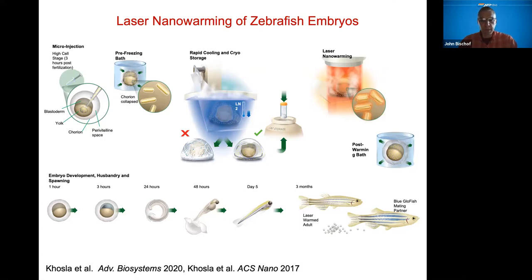So for the zebrafish, this is particularly exciting because, as I mentioned, no one has actually been able to cryopreserve this system, and many people have tried. So we finally were able to do it in 2017. We brought back embryos that were actually intact and growing, although none of them hatched. And then this year, we just published on the follow-on study to that, showing that we could get them to actually hatch. It's still low percentages, but this is a first, if you will, in terms of this type of technology.